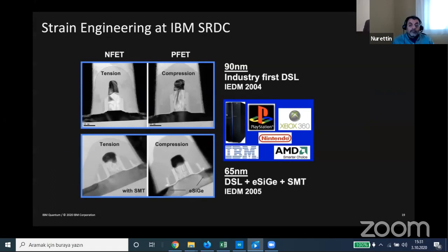So instead of doing it through lattice mismatch as described in the previous study, for 65 nanometer, we had to overcome additional pitch scaling. So we introduced additional strain. So we introduced embedded silicon germanium. And these resulting devices indeed were successful in boosting performance and were used in commercial devices.